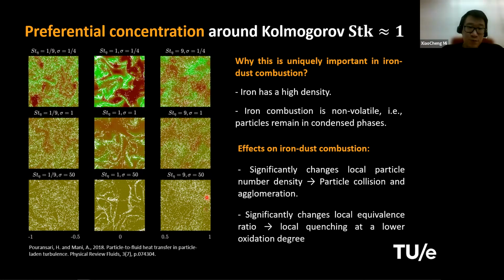So why this is important and uniquely important for iron, I think there are 2 reasons. One is that iron has very high density compared to other solid fuels like coal or even aluminum or sprays of liquid fuels. That's number one. They will give iron high inertia.